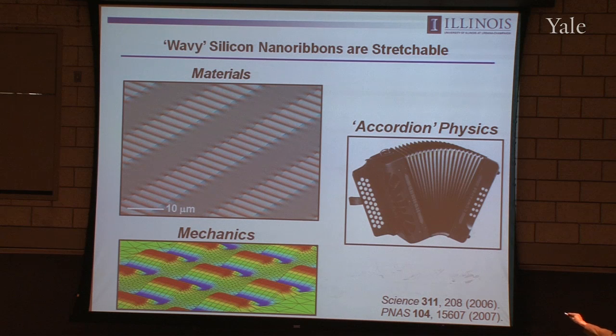The first time we saw this, sort of by accident, we thought, fantastic, that's exactly what we want. Because now we have sort of an accordion bellows made out of silicon, in the sense that if you take that underlying substrate and you stretch it out in this direction, the silicon strips can accommodate that strain in an end-to-end displacement sense through changes in the amplitude and the wavelength of the waves. So as you stretch it out like this, the amplitudes go down, wavelengths go up. There's not much strain in the silicon itself, but you have an overall stretchability, which is what you're after. If you compress it, it does the opposite thing. The amplitude goes up, the wavelength goes down.